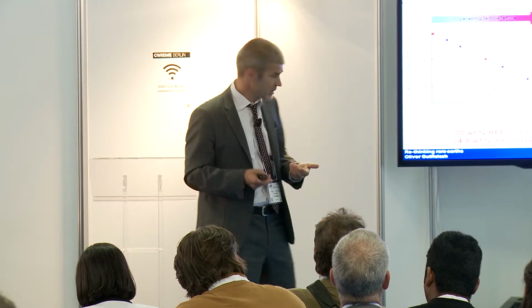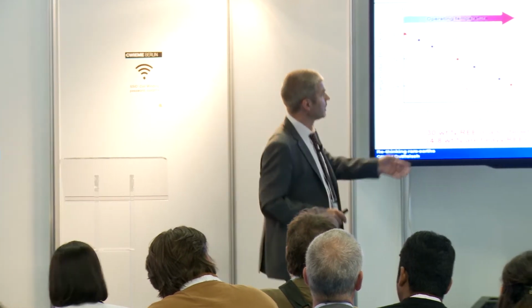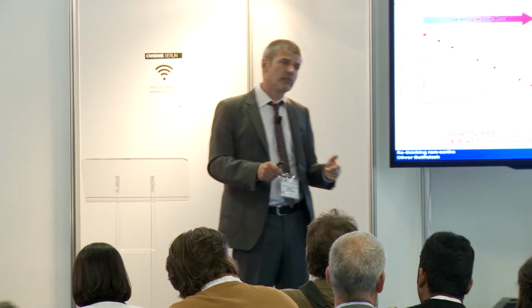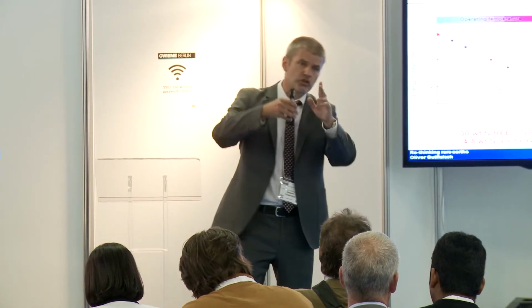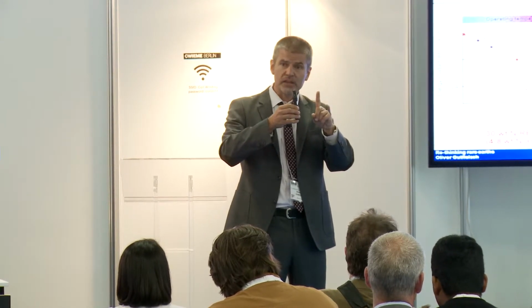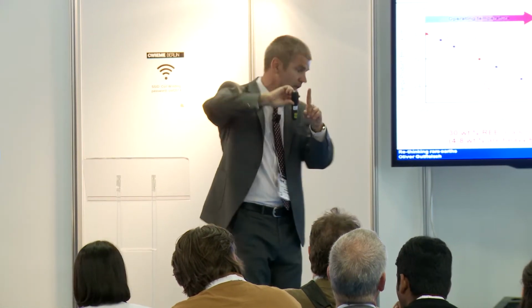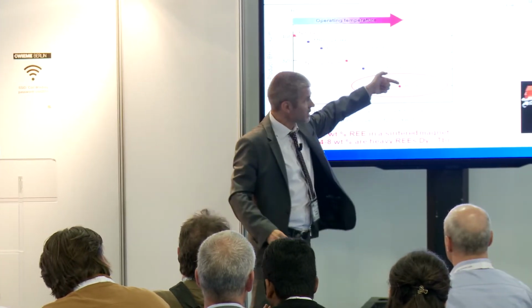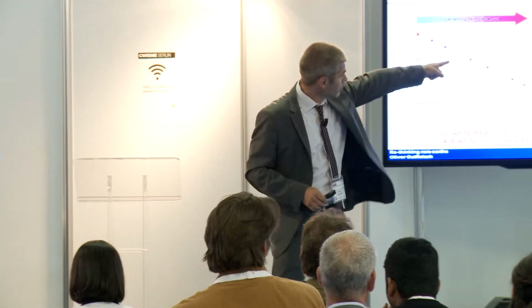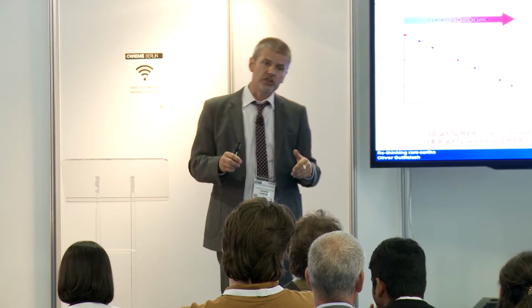So for MRI imaging, we have no temperature demand. We don't need heavy rare earths. But for the motors, we need to replace the light rare earth, neodymium, with the heavy rare earth, dysprosium. Just one short excursion: the iron couples parallel to neodymium, and we retain a high magnetization. Dysprosium, the heavy rare earth, couples anti-parallel, and that's why we have a decreased magnetization, this negative slope shown up here. But we also have the positive effect that the anisotropy of the dysprosium is much, much higher, so that we actually gain in temperature stability for the application.